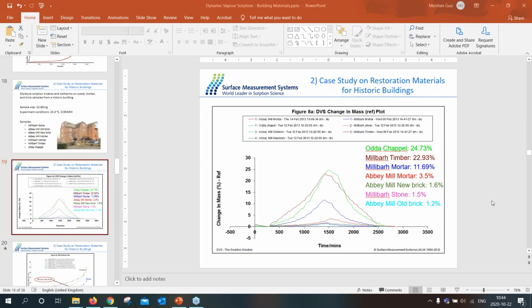Thank you for your question. Depending on your sample, it can absorb quite a lot of water. For this sample, the green line here is also not reaching equilibrium very well for the high percent RH, like 90 or 80% RH. In this case, because it's absorbing a very large amount of water, you can either increase the step time, like the maximum step, for a longer time, or you can use a smaller amount of sample, so it will absorb the water very quickly and reach a better equilibrium in a certain time, just by reducing the amount of sample used for the experiment or just increasing the time.